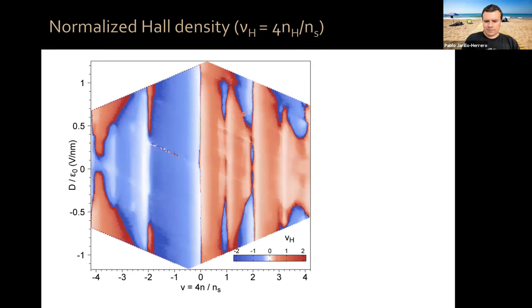So if you multiply by four, remember by four because of spin valley, and then divide by the number of electrons per Moire unit cell, okay? This is the equivalent of the filling factor, but for the free carrier density available for transport, okay? So we can measure that quantity, the normalized Hall density, as a function again of filling factor and displacement field.